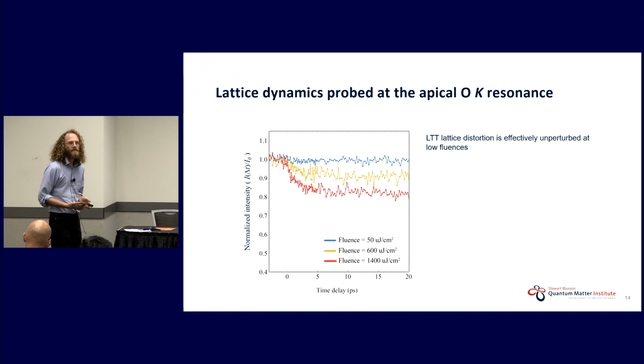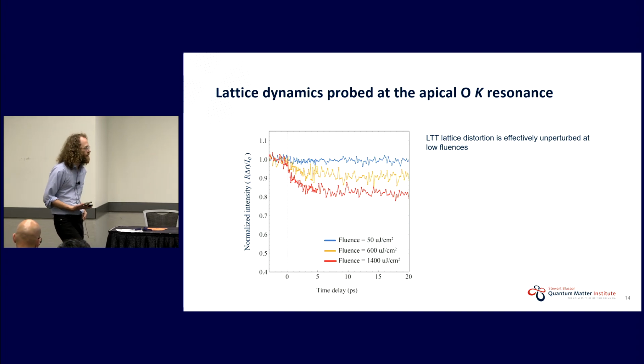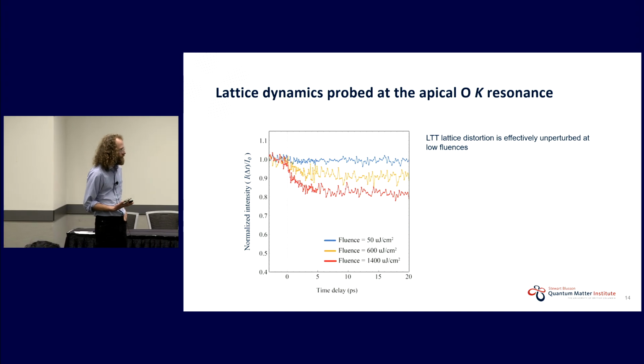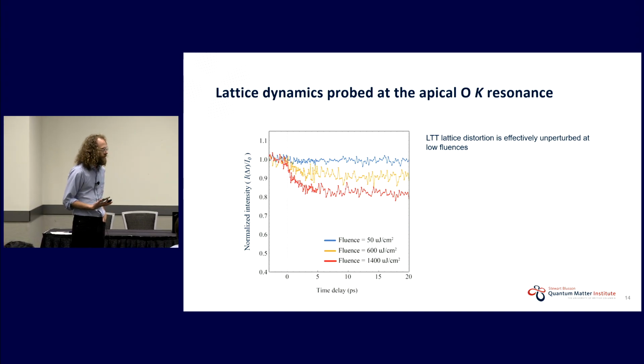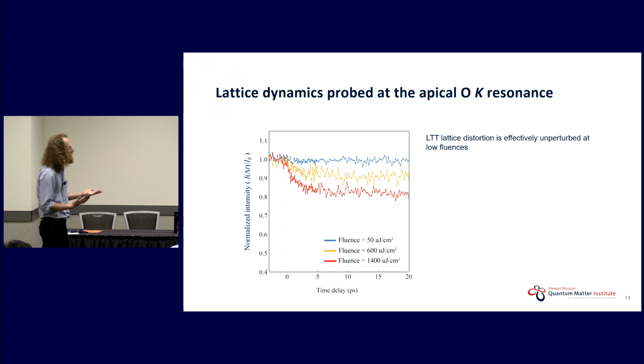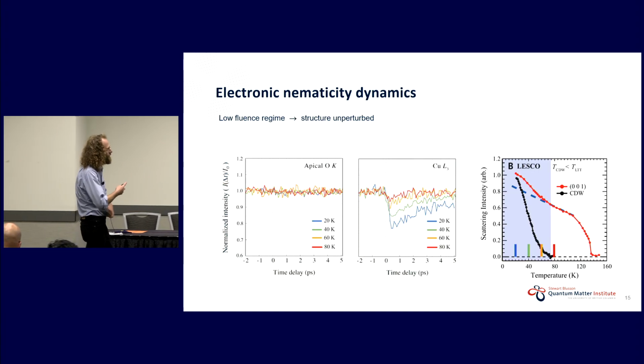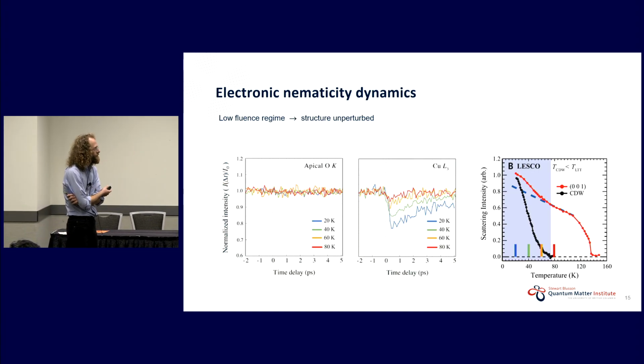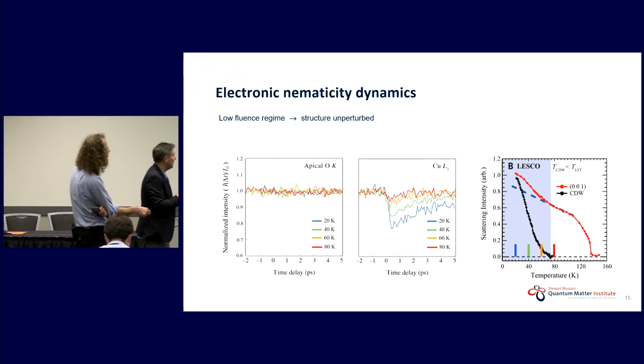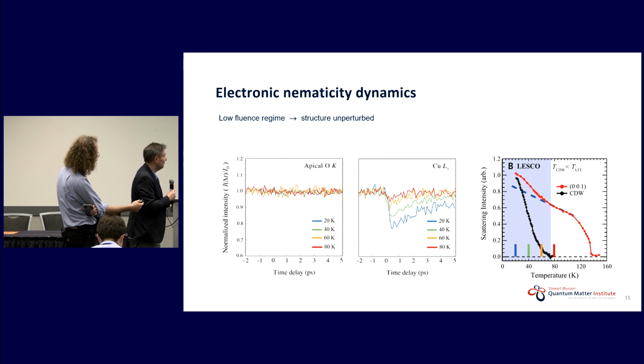More questions? Can I ask a quick one? You mentioned at some point these quasiparticles will then recombine into the charge density wave. Could you extract a time constant for that effect? Well, wouldn't that be this one? If we try to fit this naively, we get something on the order of 1 picosecond, but strongly fluence dependent.